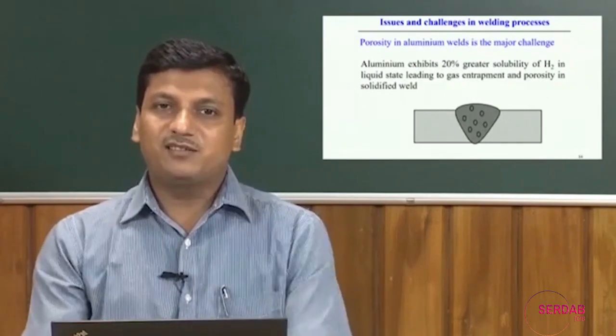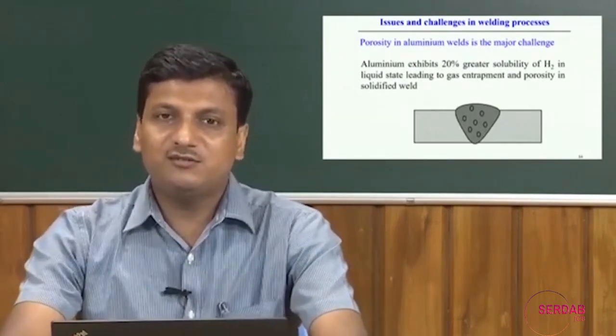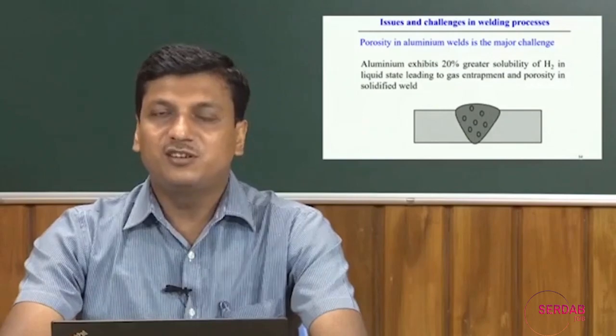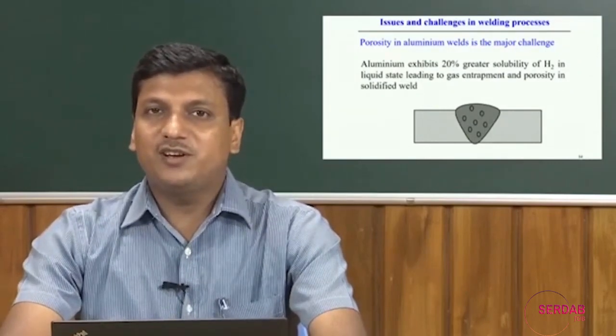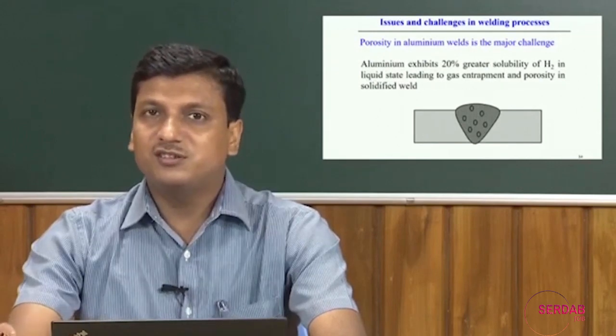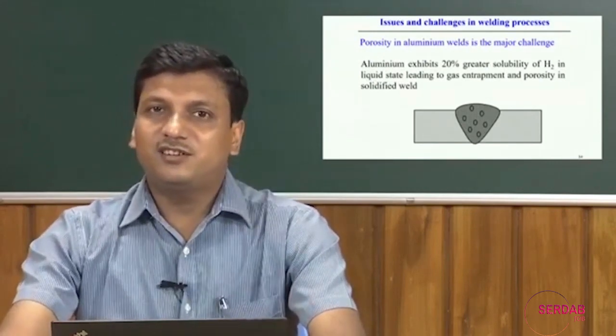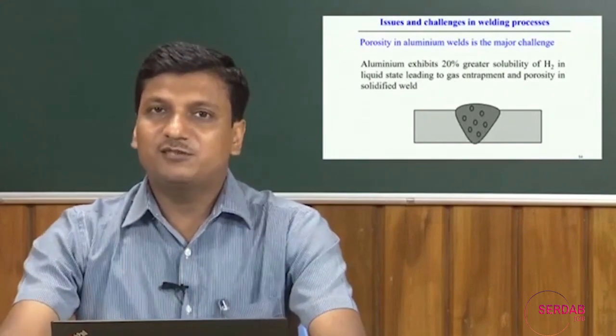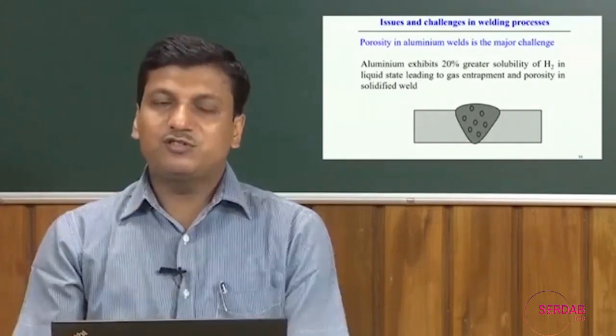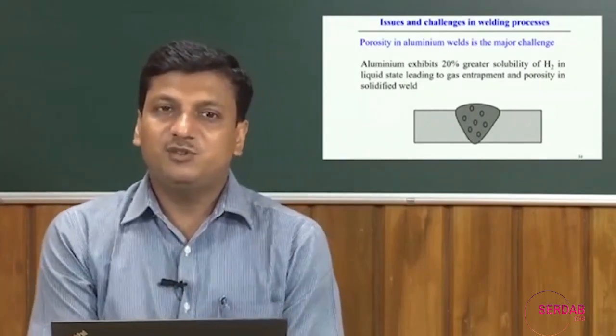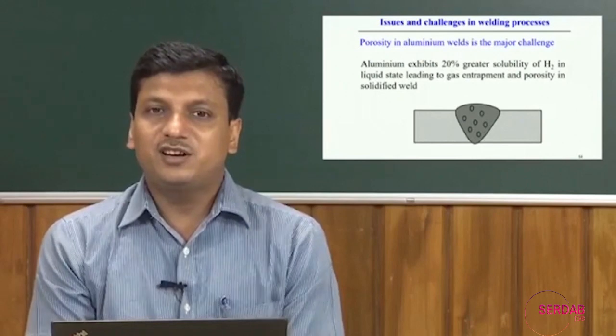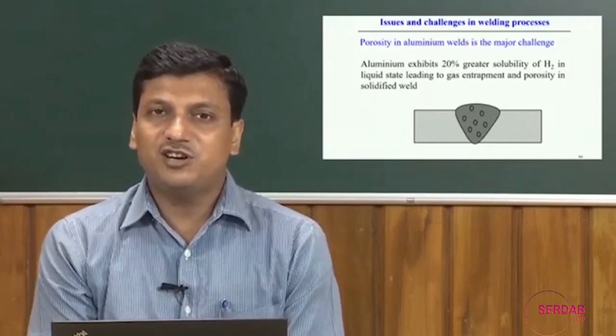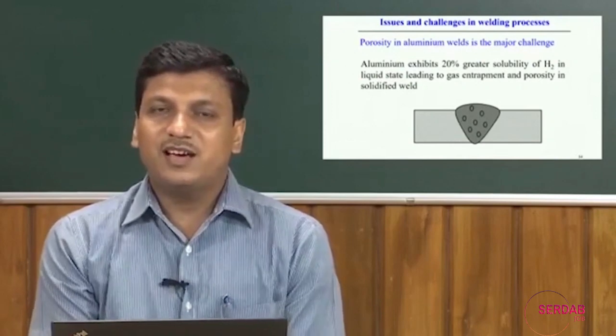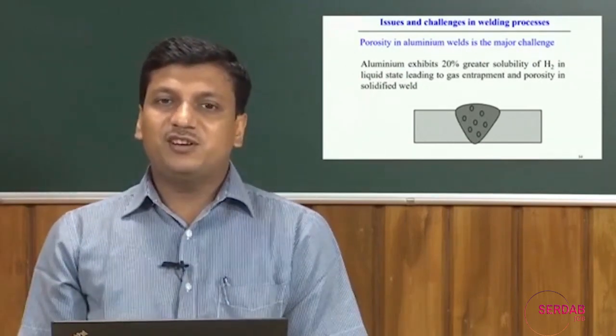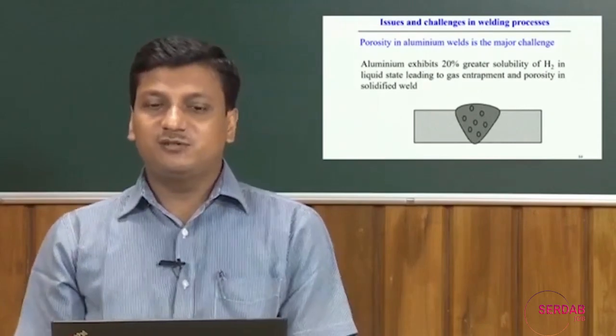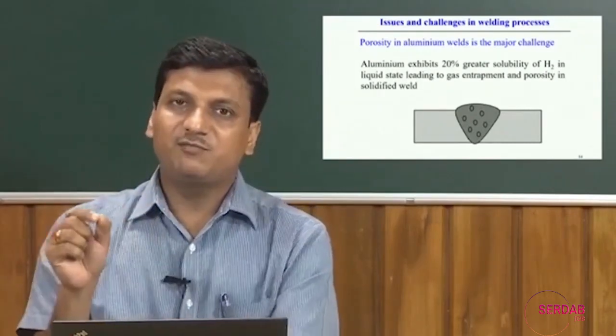Apart from that, there is another challenge in the aluminum welding process. In most cases, welding of aluminum using a conventional welding process is not easy, unlike welding of steels and ferrous materials. Porosity in aluminum welds is the major challenge, because aluminum exhibits 20% greater solubility of hydrogen in the liquid state at high temperature, and that gas may be entrapped and creates porosity in the solidified weld.